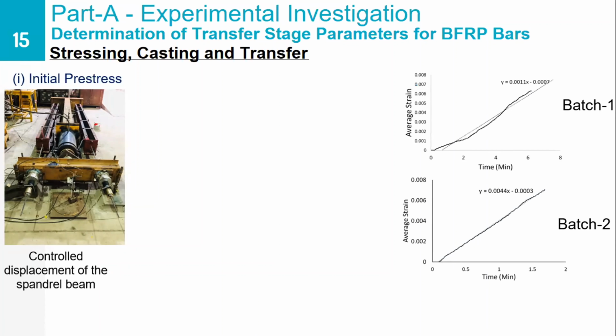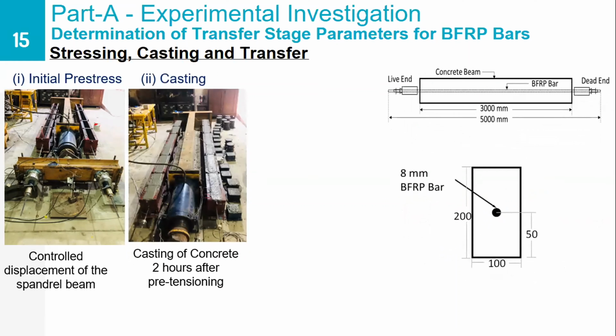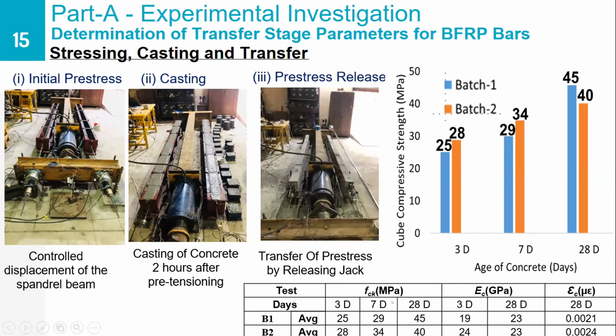So this is the loading rate that has been applied in the specimens. And after 2 hours of pretensioning, the concrete beams have been cast in the formwork which have been prepared along with the test frame. So these are the material properties of the concrete. The material properties were tested at 3 days, 7 days, and 28 days. And the 28-day compressive strength, this is the cube strength, of course, and that is what we commonly use in India. It's around 45 MPa, between 40 to 45 MPa for the two specimens that we have cast.